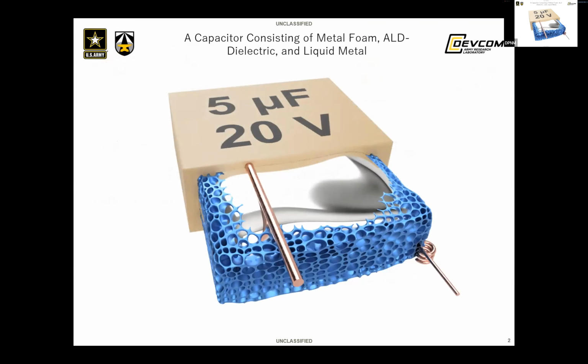I set out with a simple task of trying to make a new geometry of a basic capacitor, and you'll get to judge at the end if I passed or failed. So this capacitor consists of a nickel metal foam bottom electrode that is perfectly and conformally coated with an ALD dielectric. That could be ALD Hafnia, ferroelectric, or antiferroelectric. At ARL, we also have proper ALD antiferroelectrics like lead hafnate. And then we need a counter electrode that can fill all those nooks and crannies. And the best idea that I had was to fill the whole thing with liquid metal.